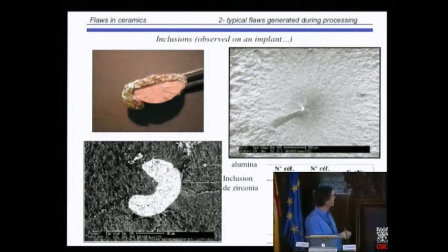Here is alumina, femoral heads again, and we have tested 7 femoral alumina heads, and this is the number of the head, and this is the load to failure. We had one head that was lower in terms of fracture load compared to the others.